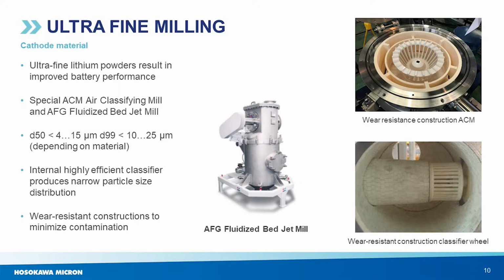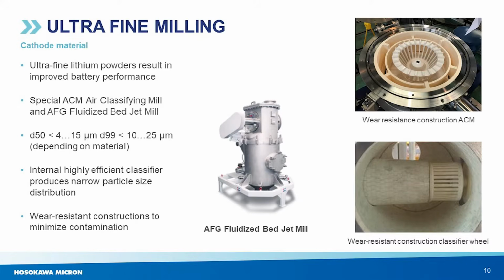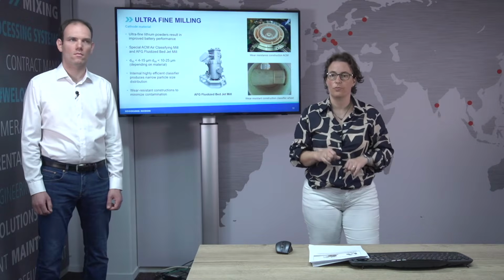Hosokawa uses dedicated impact and jet mills in special execution in order to produce an extremely fine and narrow particle size distribution. Top sizes are 10 to 25 microns and a D50 of 4 to 15 microns, depending of course on the product. All mills include special designs for wear protection with ceramic. This ensures a high purity of your product.